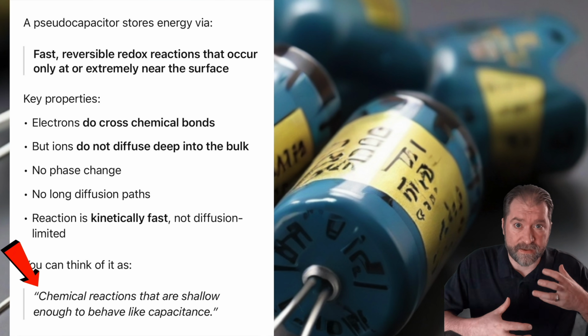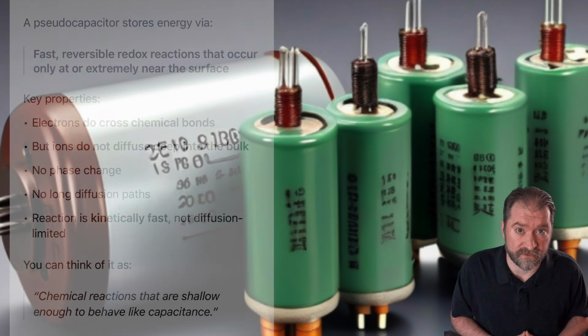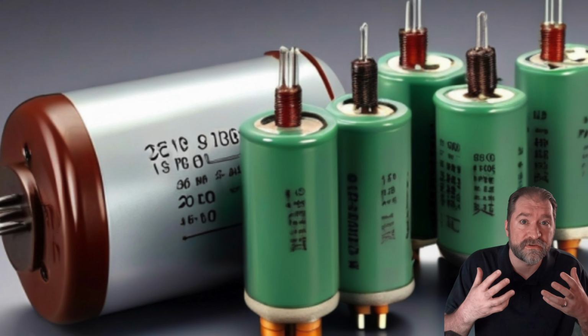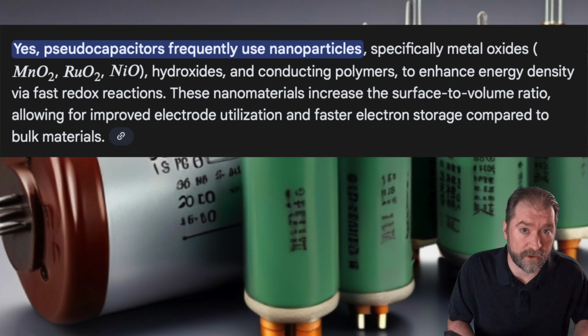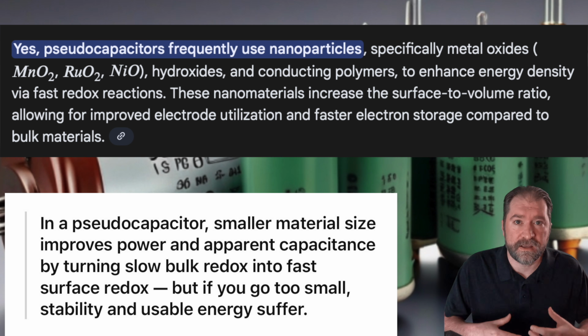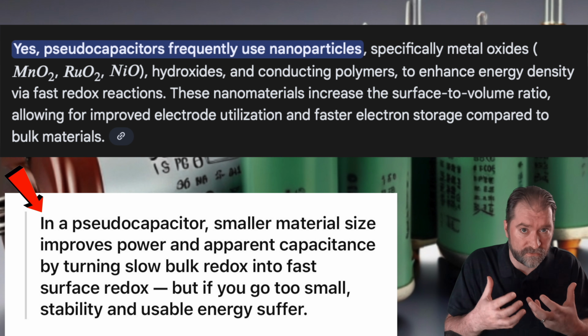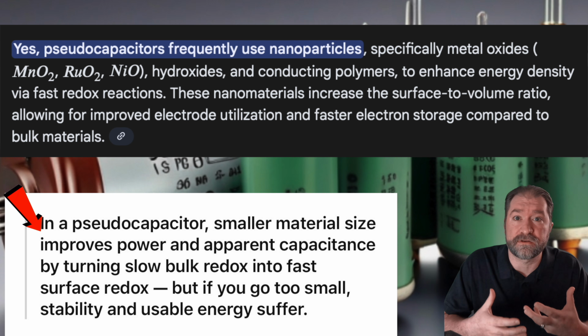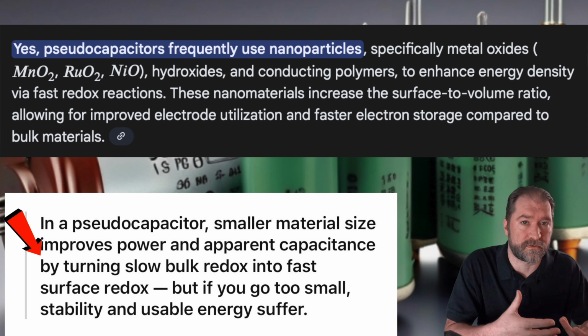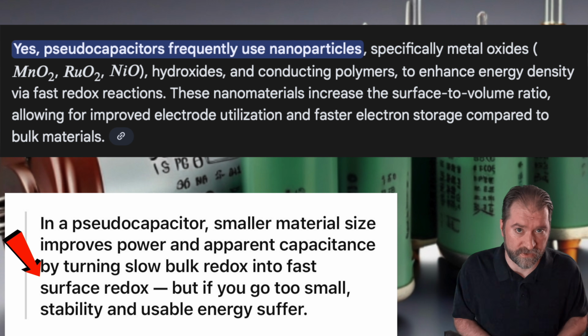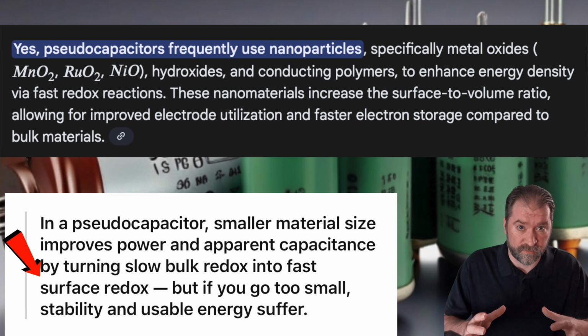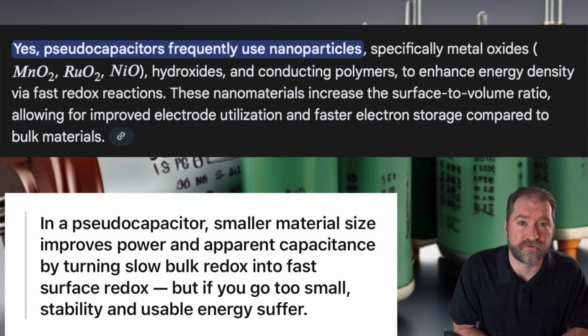There's a lot of different chemistry being used in a pseudocapacitor, but another major characteristic is very small, as in nanoparticle material size. In a pseudocapacitor, smaller material size improves power and apparent capacitance by turning slow bulk redox into fast surface redox. To a point. But if you get too small, stability and usable energy suffer.